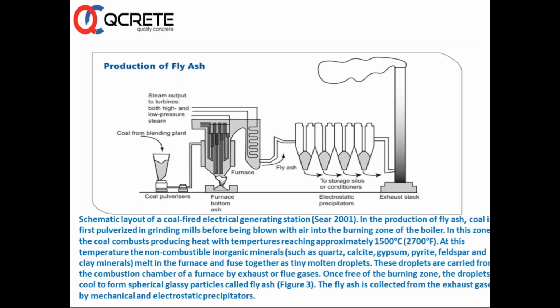The finer the fly ash, the better its performance, because it is found that fly ashes with particle size between say 5 to 30 microns are very effective for making good concrete. Fly ash particles of higher diameter, coarser than 45 microns, tend to give very low reactivity, and hence such thicker particles may sit as dummy particles in the body of concrete and are not preferred.